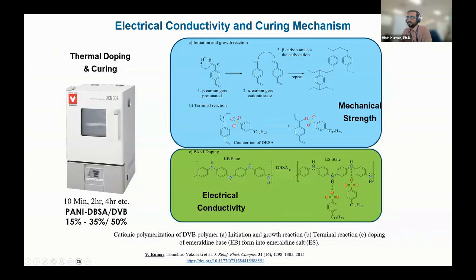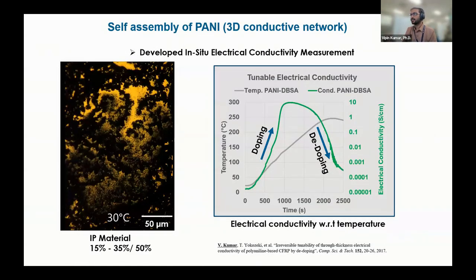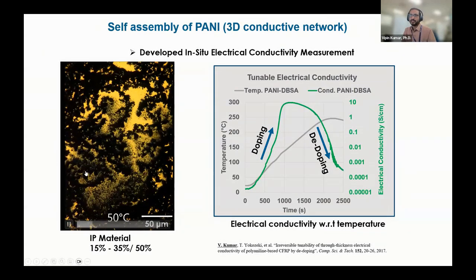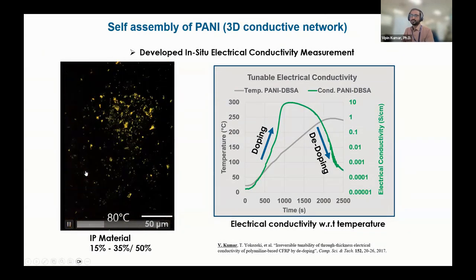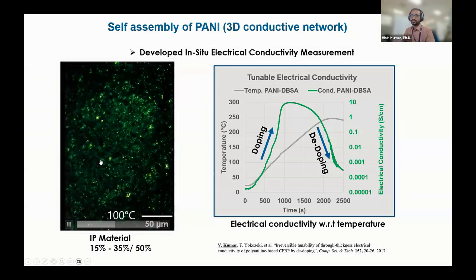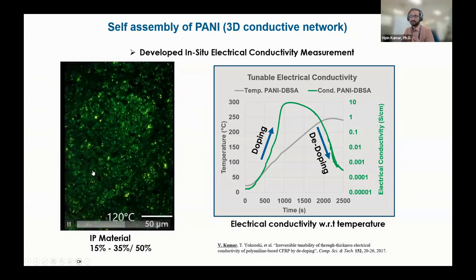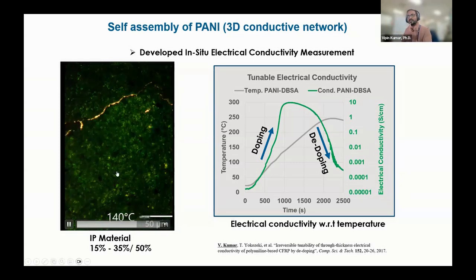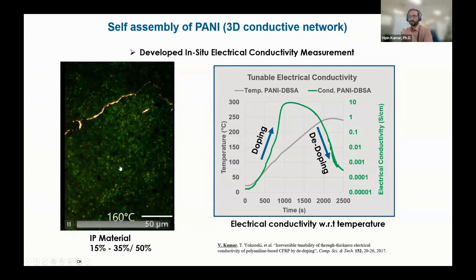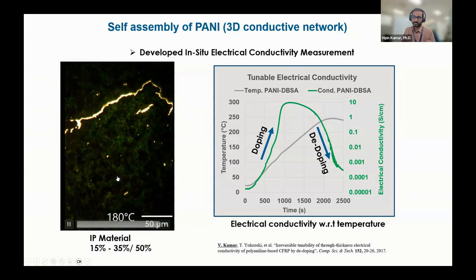So that's the chemistry I talked about, but let's talk about why this system becomes electrically conductive. Polyaniline is the black part, and the yellow one is the resin. When we heat it and the polyaniline gets doped, it breaks down into smaller molecules and creates a 3D network, and the green means electrical conductivity. But if you start heating too much, you can see that it will start to go back to its black color, which means it's de-doping.